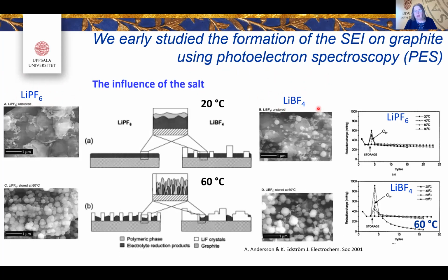And this is a simple study where we actually showed the influence of the salt, where we compared LiPF6 and LiBF4. And at that time, at the end of the 1990s, it was not really clear. We worked with a battery producing company in Denmark that existed at that time, and it was not clear whether they should use the more in the laboratory stable in the bottle, LiBF4, or the more unstable, LiPF6, a little bit more expensive. LiBF4 was better with the cathode, but it was something weird with the anode. And we could show by making some kind of simple storage and cycling experiments, pre-cycling an electrode 3 times, storing it for 1 week at a certain temperature, then starting to cycle it again.